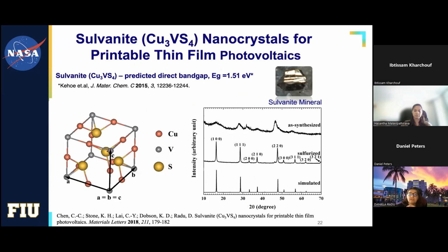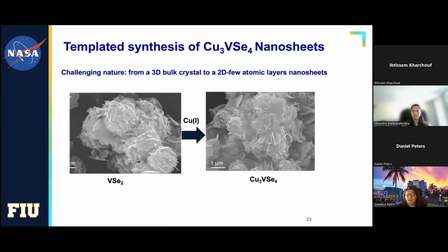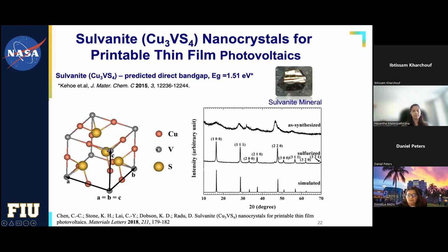So we started by trying to adapt what we learned earlier about copper zinc tin sulfide and create nanoparticles from sulvanite copper vanadium sulfide. This is the structure of the material, and we successfully obtained nanocrystals, and we published this for printed thin film photovoltaics.